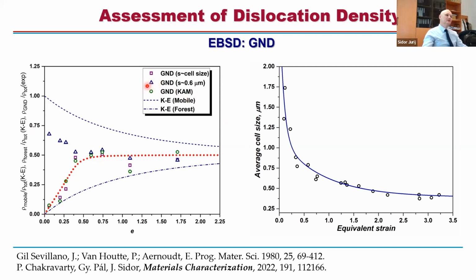Look at the results of our measurements. If you work with a constant step size, for instance 0.6 micrometers, here you see those triangles, right? And then you have GND estimated by kernel average misorientation. So completely different behavior. In one case, it tends to drop. In another case, it tends to increase. However, when we calculated the GNDs with the step size or kernel radius comparable to the cell size, we obtained almost identical results to those which we observed by this kernel average misorientation.